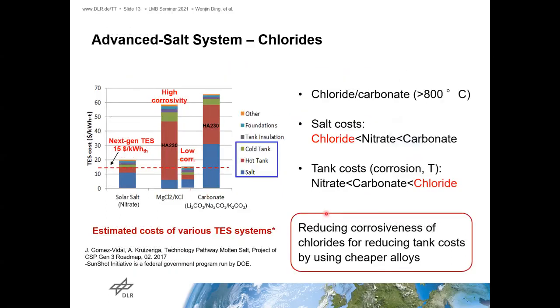But for the high temperature next generation molten salt heat storage technology, we have to choose the right salt, as shown in this diagram. Now we use nitrate, yeah, but we want to increase the temperature. We need more thermally stable salt like chloride or carbonate. But compared to the chloride, the carbonate has to use lithium carbonate to have a low melting temperature, but it will lead to very high material costs. So now we focus on the chloride system.